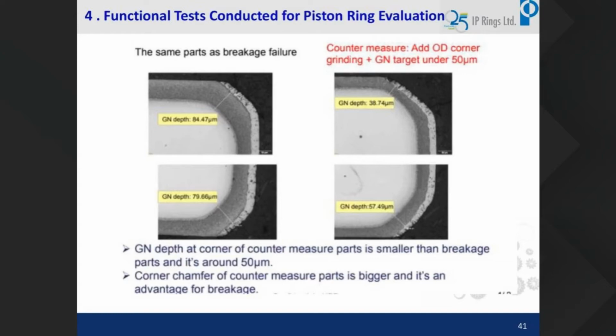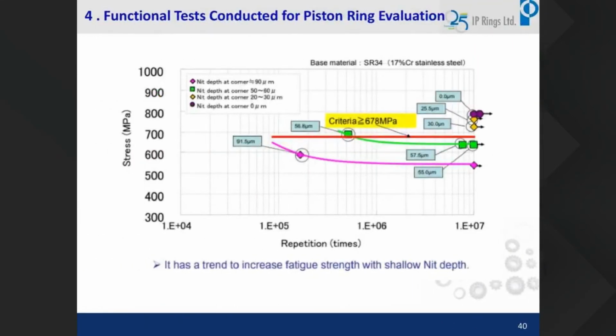Also, we have a collaboration with Nippon Piston Rings Japan. This is the cross section of the piston ring. This is the nitrided layer, and on top of it is the PVD coating. If you see in the corners, what our collaborator recommends is that the GN depth should be as minimal as possible, less than 50 microns, or close to around 50. If you see the previous slide, with the nitriding depth, fatigue failure also happens. This pink one is the piston ring with around 90 microns depth, which is not meeting the required fatigue cycle time.